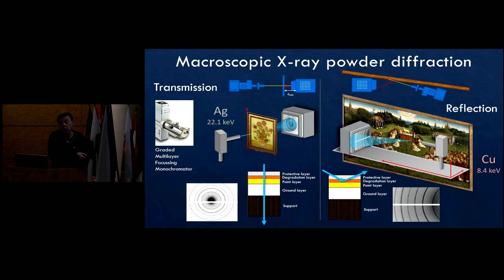But of course, that doesn't work if you have a very thick wooden panel, as you can see here, because then the beam would not go through completely or would not go through at all. So we have more recently developed this kind of reflection geometry where the detector and the tube are all on one movable stage, and we can move that in front of very large panels. And while maybe somewhere in the future, perhaps, another Van Gogh will come to a synchrotron somewhere in the world, I can tell you this panel here will never leave its museum.